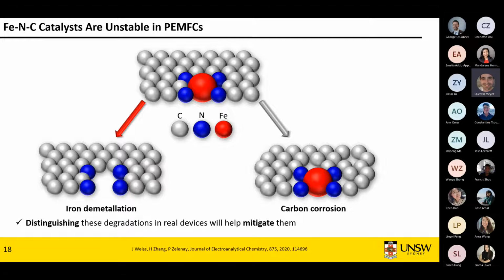Second one is you're using amorphous carbon, which is going to corrode as you operate your cell at 80 degrees and at high current densities. As it corrodes, you may end up also losing your iron site because you lost so much carbon, you're just going to, at some point, lose your catalyst as well. So it's okay, you understand what's happening, but you don't actually know how it's taking place in a real device.